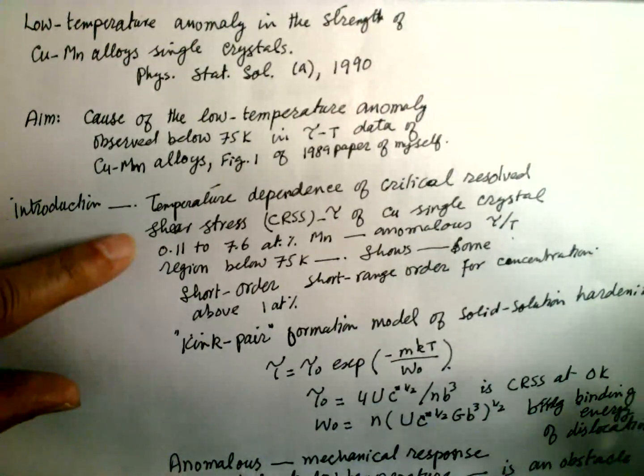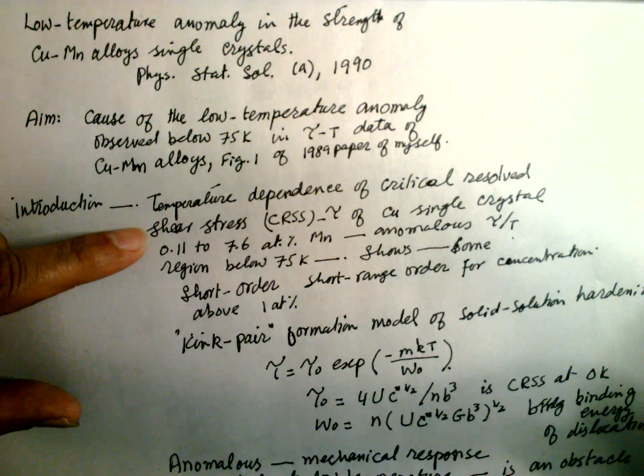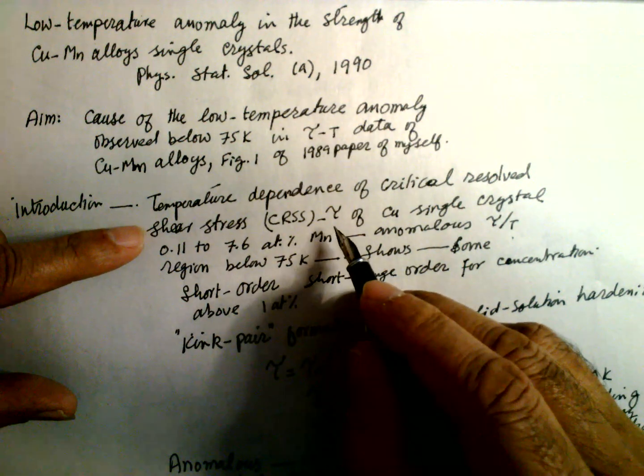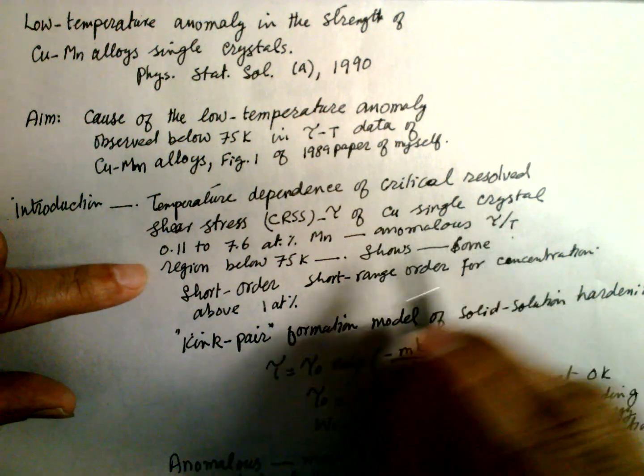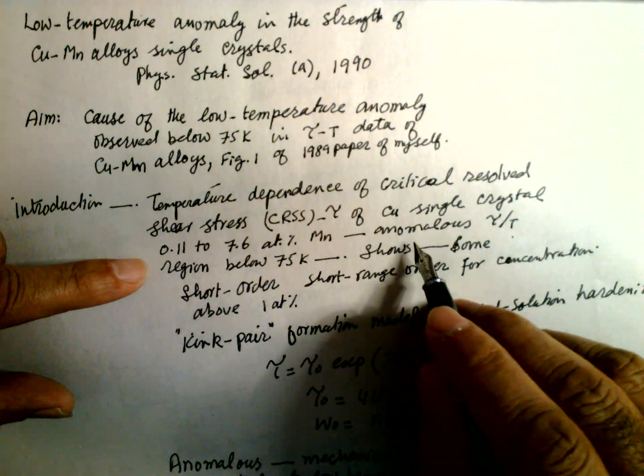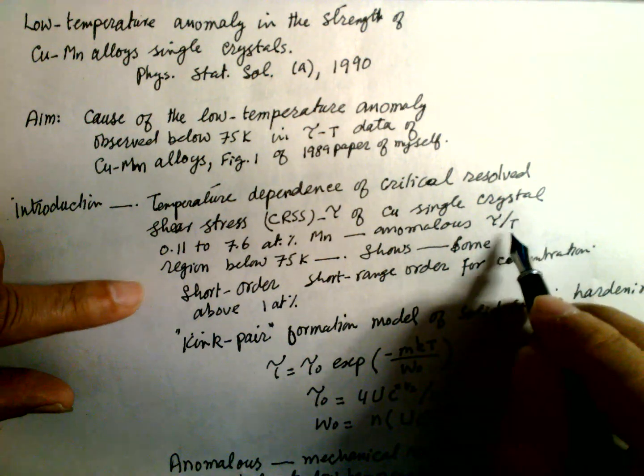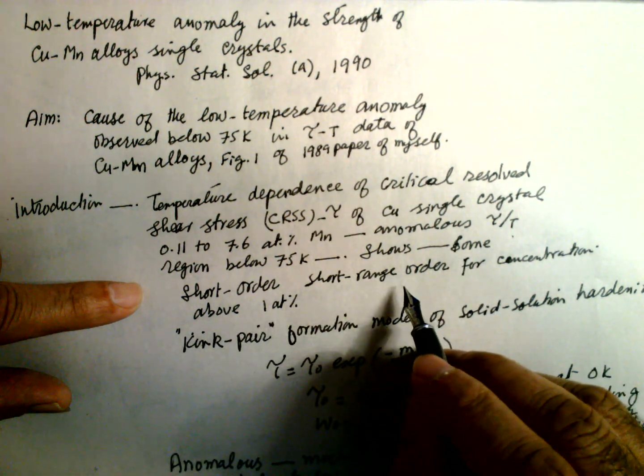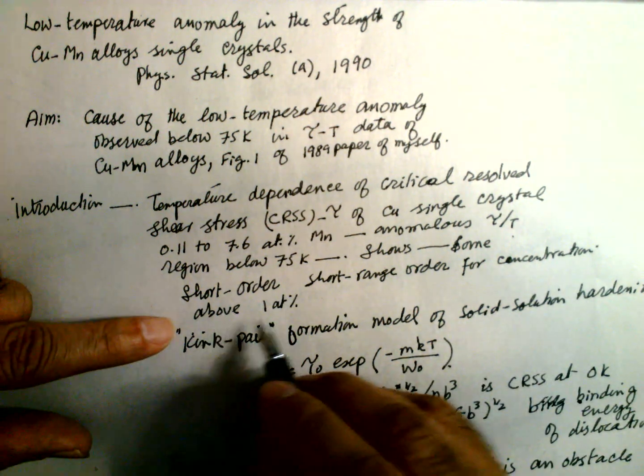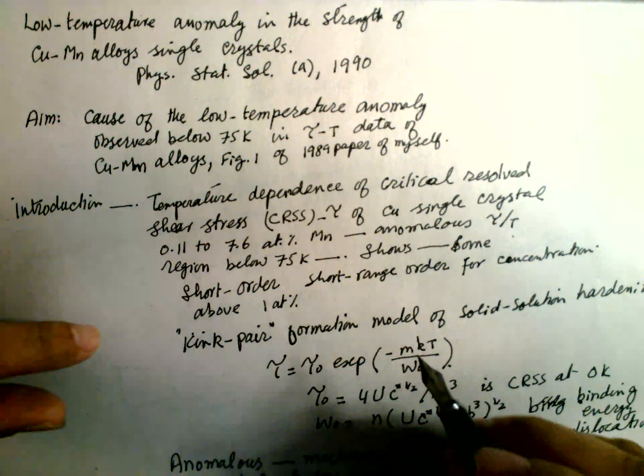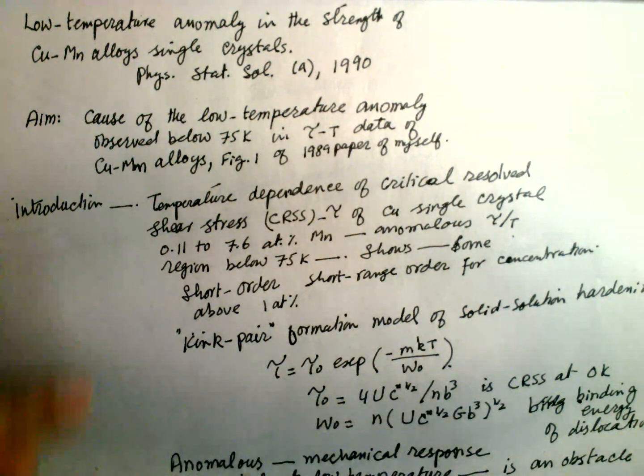The introduction of this paper is the temperature dependence of critical resolved shear stress, which I explained in my previous discussion. CRSS, represented by tau and measured in megapascal, of copper single crystal from 0.11 to 7.6 atomic percent of manganese. Anomalous behavior of tau versus T in the region below 75 Kelvin has been observed, and this shows some short range order of the concentration above 1 atomic percent. So this is the intro, and the kink-pair model has been used in this study.